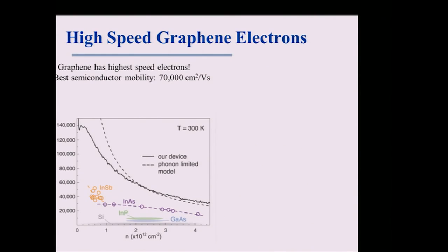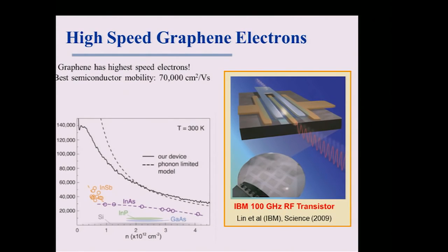Turns out, if you measure the velocity of the electron as a function of how many electrons you have, the mobility of the electron is way, way higher than the mobility of electrons in any conventional semiconductor, not to mention metal. Which means that if you make a transistor or device out of graphene, it works really, really fast. Recently, that has been demonstrated by the IBM group. They made the graphene transistor on the wafer scale and demonstrated that this transistor operates really fast when it's made of graphene. So there are some interesting applications that might be possible.